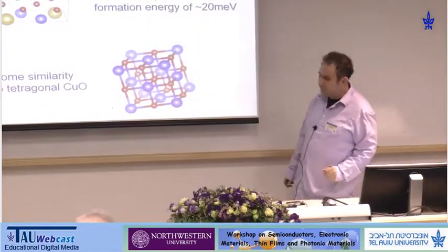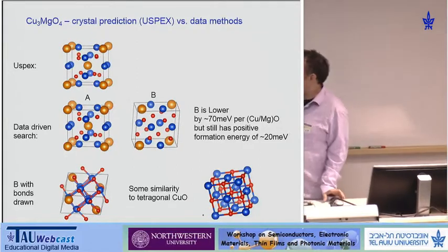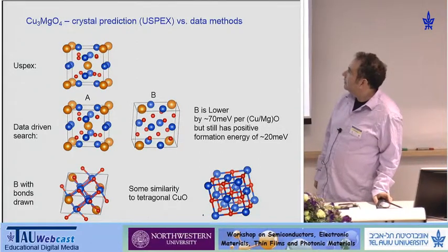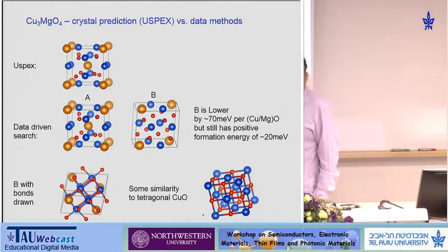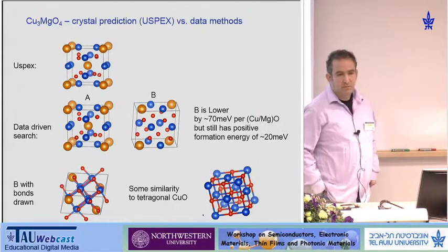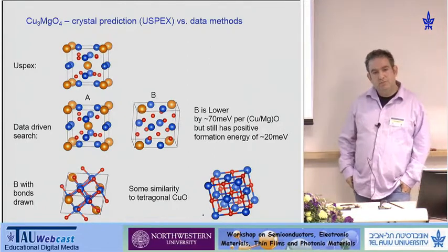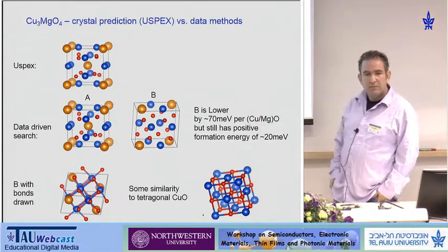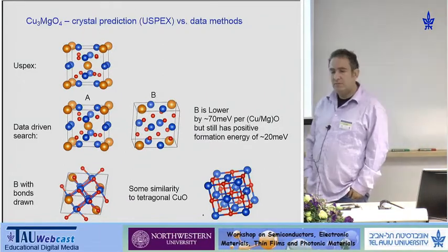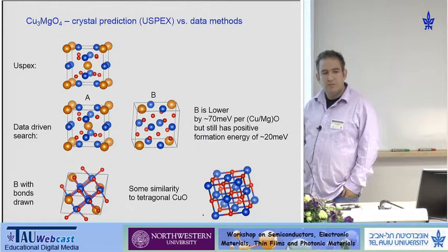Can you show the next diagram? Just a quick comment about this question, where you have this USPEX thing. If you look at the right-hand side, the final best result is that the mixture has higher energy than the endpoints. So that's the definition of phase separation. And that means thermodynamically, as you of course well know, that at any finite temperature, you can stabilize only the alloy, but never the ordered phase. So there is no ordered phase according to that, if you take that seriously.